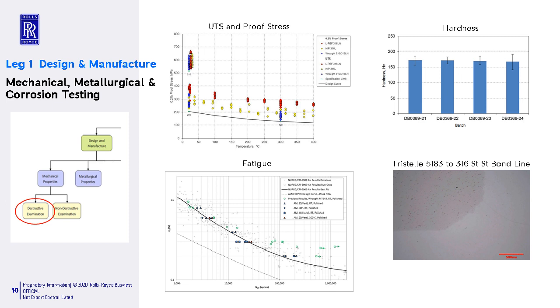We tested a number of different material batches in a number of different test orientations, all with the intent to demonstrate that material properties were equal to or better than the current wrought material specification. So in terms of mechanical tests, we did tensile, Charpy, hardness, fatigue, fracture toughness.